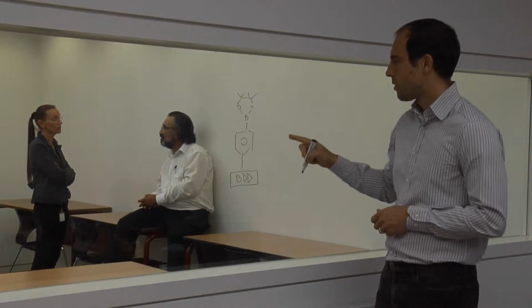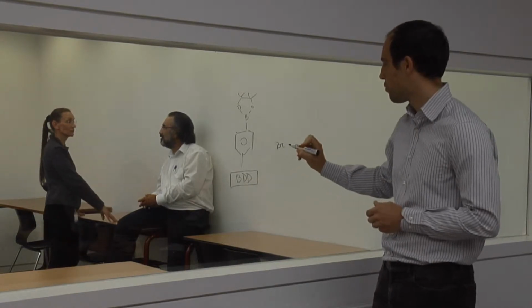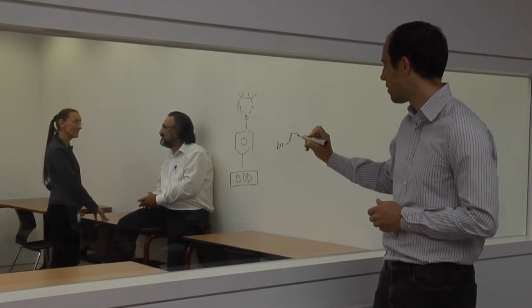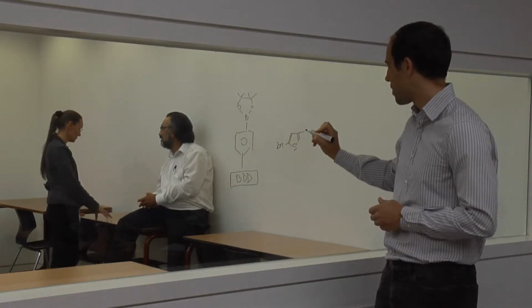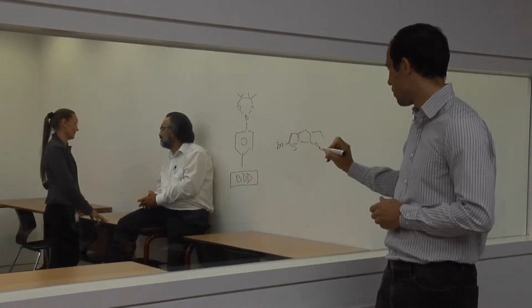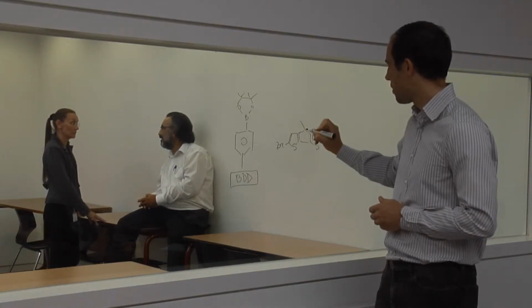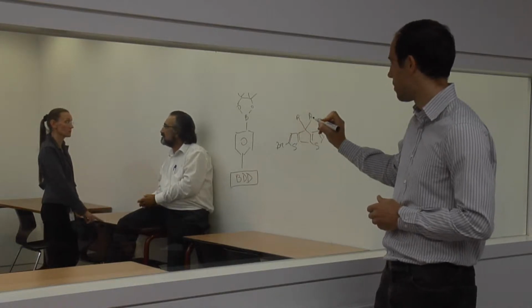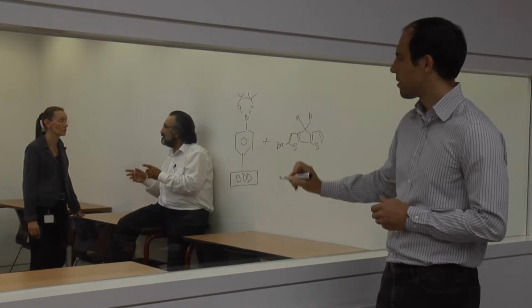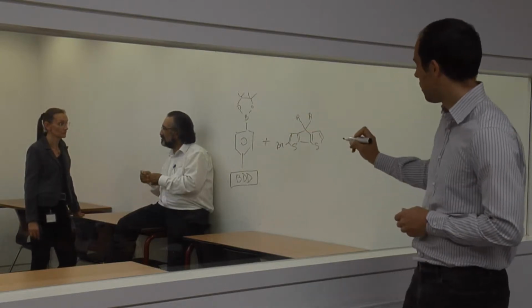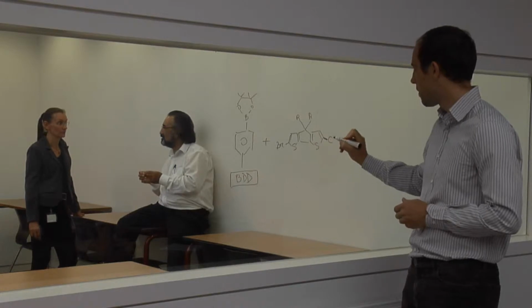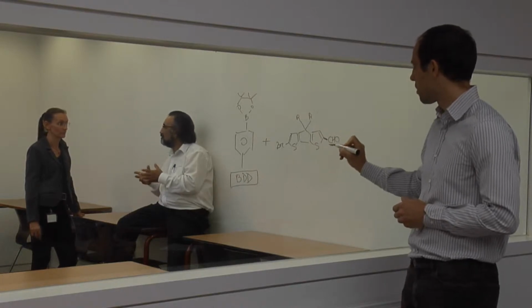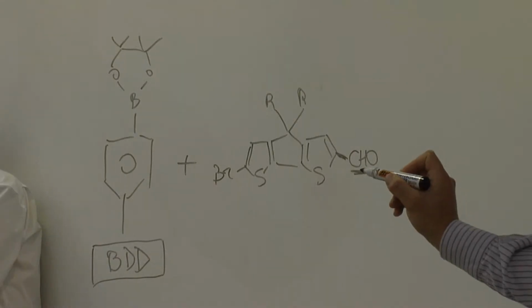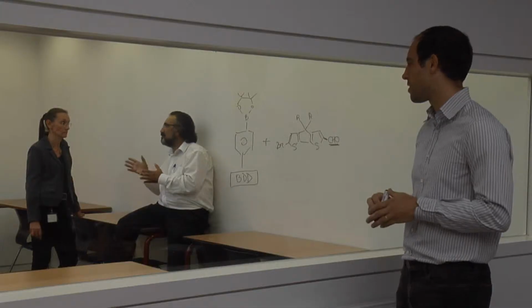Then in the next step, we want to couple a dye to this functionalized diamond, and for that we need a complementary function to the boronic ester, which could be a bromine group on an aryl. As an example, I will draw a cyclopentadithiophene, which looks like this, decorated with alkyl chains here. These two are coupled together. We have a larger structure, and in the end, at the other side, we still have a site available to couple alternative dye molecules to construct the whole diamond functionalized sample.